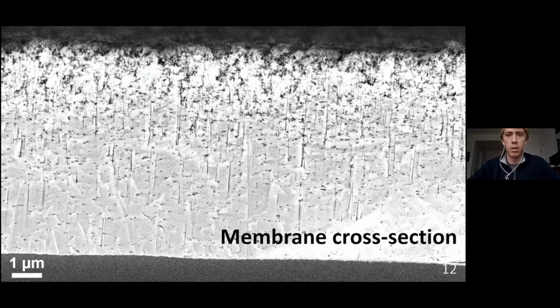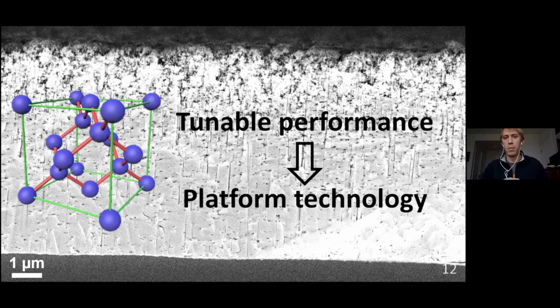Chiefly that's occurring at the surface, ideally at those pore entries. So what we are able to do is actually modify the pore diameter. And so this gives us a tunable performance in terms of what we can reject from solution, not only in terms of the pore diameter, but also in terms of hydrophilic and hydrophobic interactions, as well as other chemical interactions. And so this has bestowed with this technology the opportunity to have a platform technology where we could target different applications depending on the needs we see in industry today.